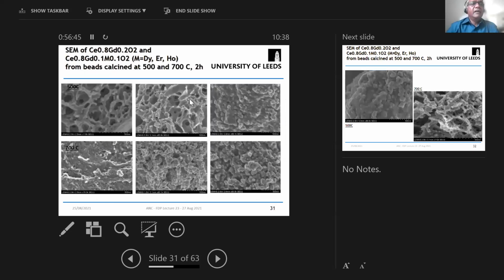Okay, so this is the SEM image of the CGO co-doped with dysprosium, erbium, and holmium from the beads that are calcined at 500. So the top line is for 500 degrees Celsius for 2 hours, and the bottom line is for 700 degrees Celsius for 2 hours. And you can see that there is a high degree of porosity in all these calcined beads. And that is one of the reasons why we believe strongly that the method gives rise to the nanopowders instead of coarse powders, and therefore doesn't need ball milling at all. It just needs breaking up the agglomerates to form the nanoparticles, which is the main advantage of this method.